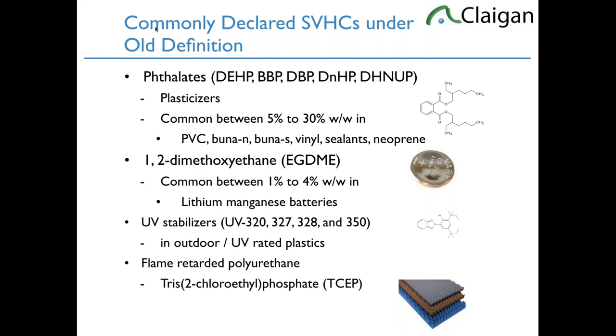the product. The other one that was common in high concentrations is TCEP, tris(2-chloroethyl) phosphate. It's one of the main flame retardants in polyurethane foam. So if you go to the baby car seat in your car, it's the common flame retardant in the foam inside. There's a good reason: the car is full of gasoline, or now often lithium. It burns quite well. You need a tremendous amount of flame retardant to make sure the baby seat doesn't burn very easily. And so that's where this comes in. So it'll be 20% of the weight of the foam. So also very high concentration.